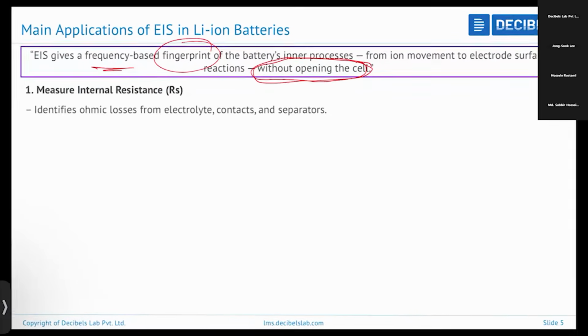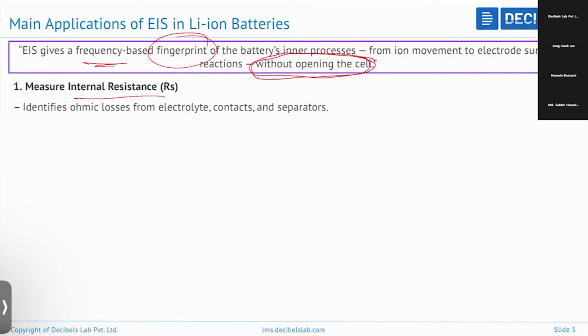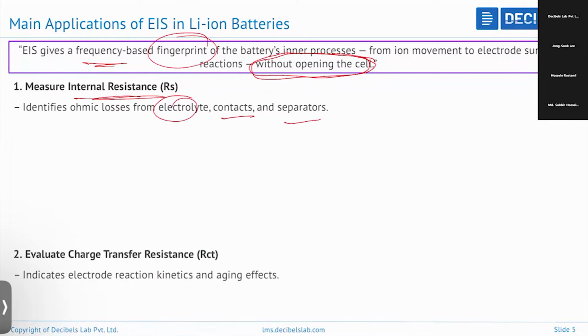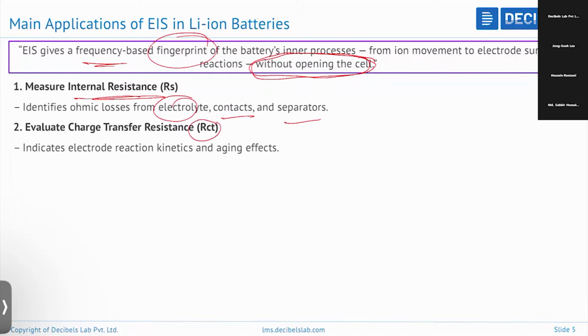By using this EIS technique, we can understand the internal resistance. This corresponds to the ohmic losses from the electrolyte, contacts, and separators. It also evaluates the charge transfer process. Charge transfer is the electron transfer in the graphite to the lithium, where it undergoes a reduction reaction. This basically defines the kinetics of the reaction, and that is mainly based on Butler-Volmer kinetics and Tafel kinetics. I have explained in detail about this charge transfer process in some of the videos in that course.